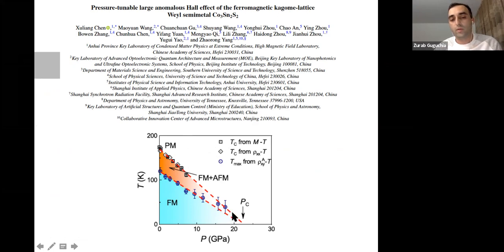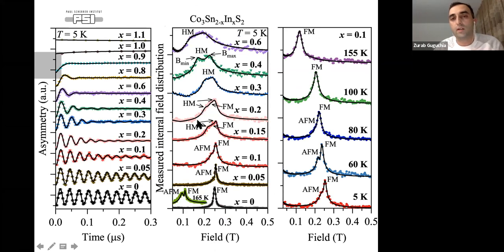Of course, when you apply pressure, you compress the system, and it seems like this compression does not break the ferromagnetic state until very high pressure. But instead, what we did, we studied the indium doping effect. In the case of indium doping, we are putting in some carriers. So we dope the system, but at the same time, we also expand the lattice. So it's the opposite effect of hydrostatic pressure.